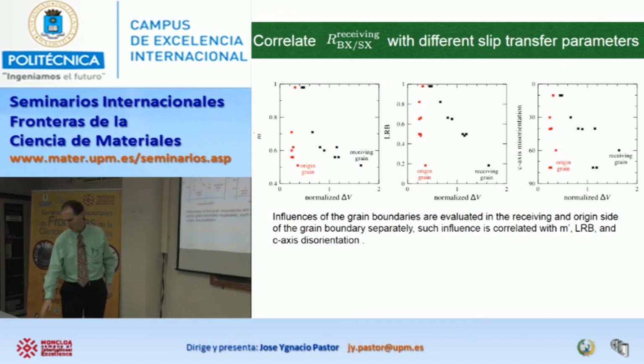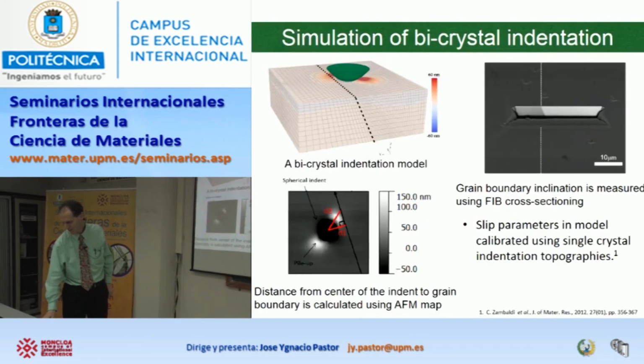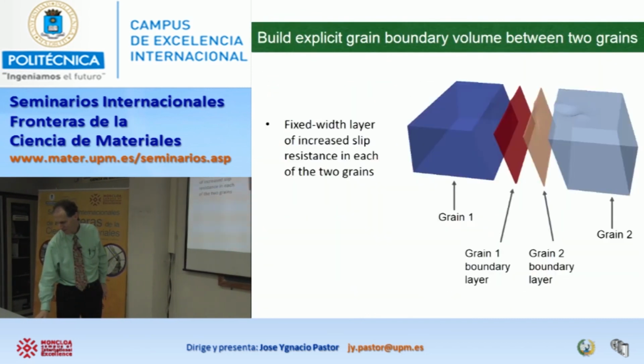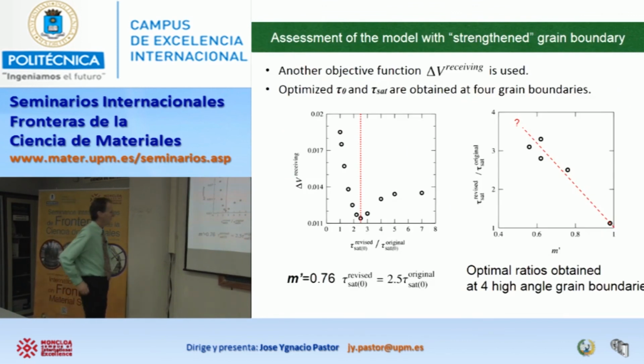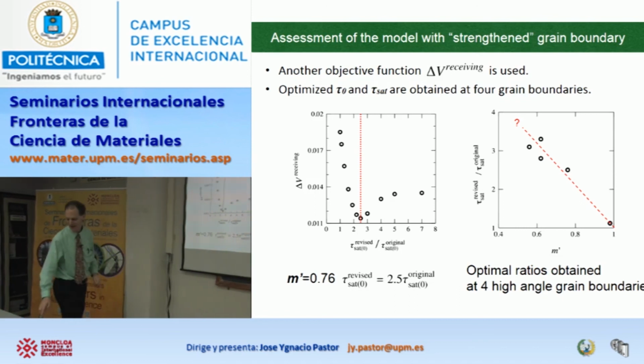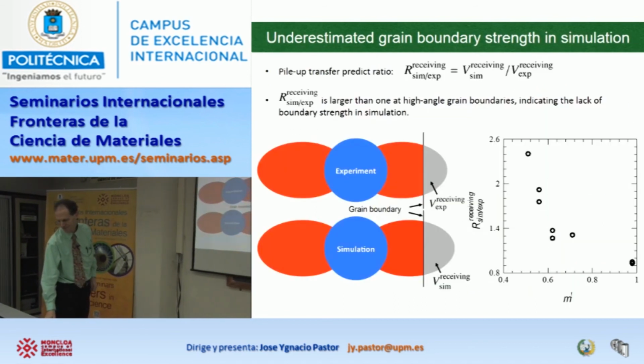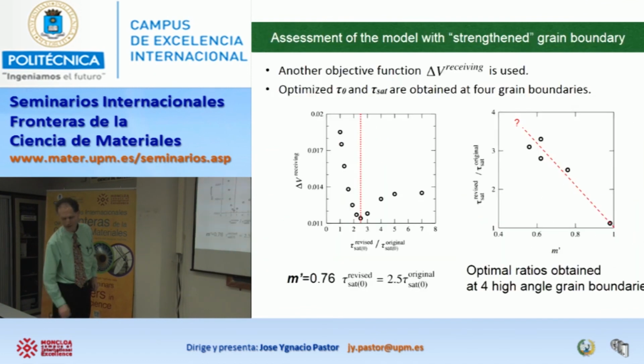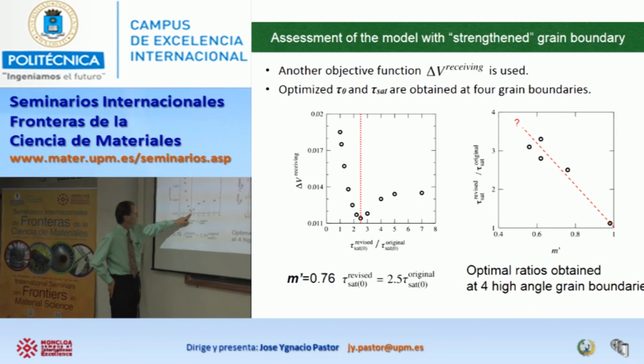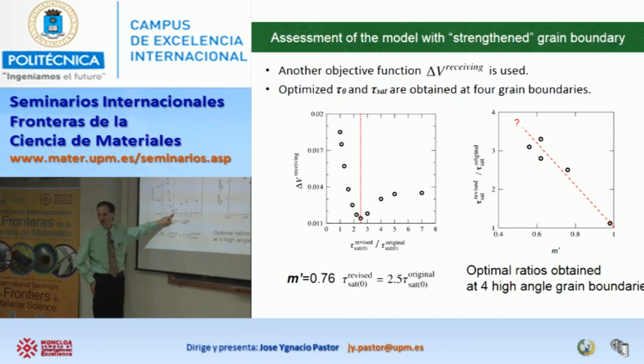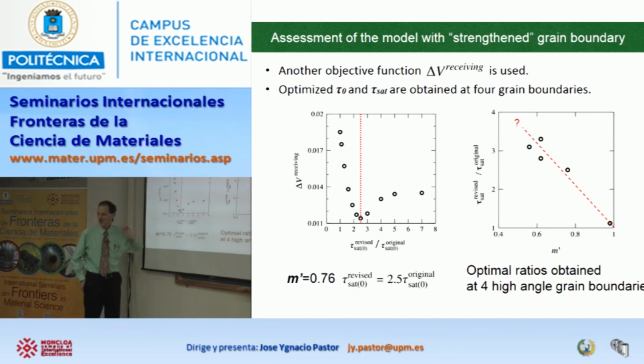Let's see. I'm slightly out of order here. So if I play this game, then I can find what value I have to increase the hardness of this layer to where I get the smallest difference between my simulation and the actual experimental measurement. So this change in volume here represents how good is my simulation at predicting the shape change versus reality.